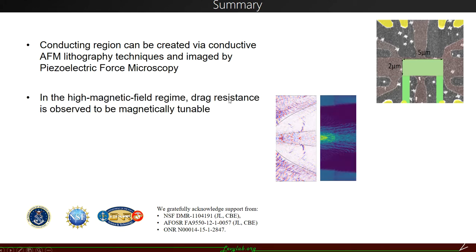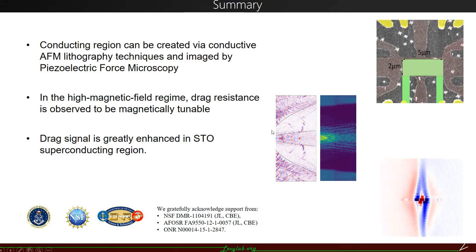For a short summary, conducting region can be created by conductive AFM lithography technique and imaged by PFM. In a high magnetic field region, drag resistance is observed to be magnetically tunable, and drag signal is greatly enhanced in SrTiO superconducting region.